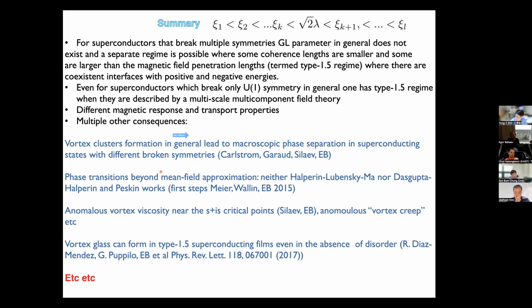In general, the phase separation into vortex clusters and normal state also leads to phase separation in domains with different order parameter symmetries. Because of the existence of the large cores, they can lead to inducing a different type of superconducting order near vortex clusters. So you may have not only phase separation in the vortex clusters, but near vortex clusters you could have S plus iS superconductors, where time reversal symmetry is broken, and in the Meissner state you can have an S-wave superconductor. And there are many other consequences. So I think this concludes my talk, and thank you very much.